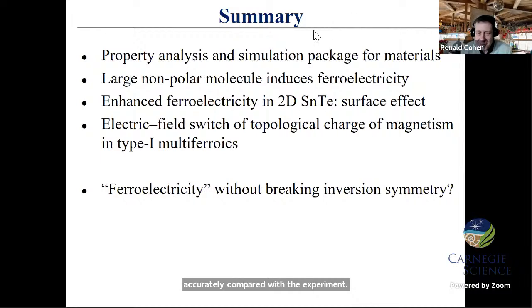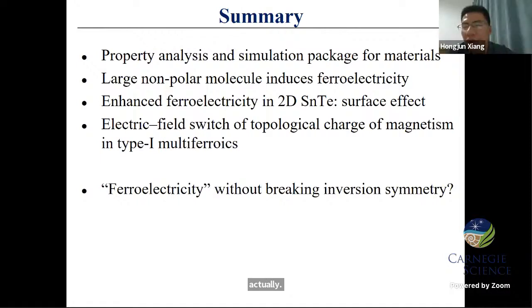Oh, okay. Yeah, this is a good question. So how accurate can we calculate the spin interaction parameters? For example, in our density functional theory calculations, we have some parameters, for example, the U value in the Hubbard U calculations. If you change the U, it will change the Dzyaloshinskii-Moriya interaction. I can only say that usually the order of magnitude of the Dzyaloshinskii-Moriya interaction is similar to the experimental results.